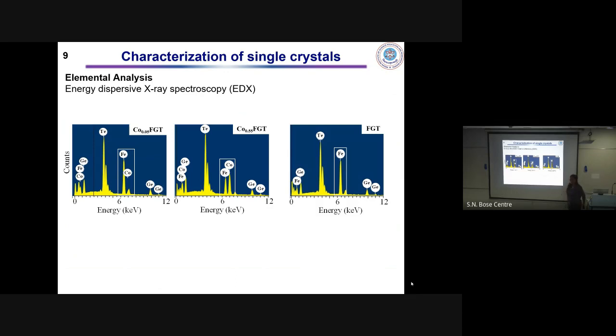But why did you dope cobalt? Because there is a report where you put nickel and the transition temperature increases. When we started working on Fe3GeTe2, there was no report on these systems, but that's not the only reason. When Fe3GeTe2 has been doped with nickel, the magnetization goes down, and Ni3GeTe2 is absolutely non-magnetic. However, Co3GeTe2 is still not stable, its structure is still not known. So we were motivated to see what is happening between iron, nickel, and cobalt, with cobalt sitting in between. That is one of the reasons.